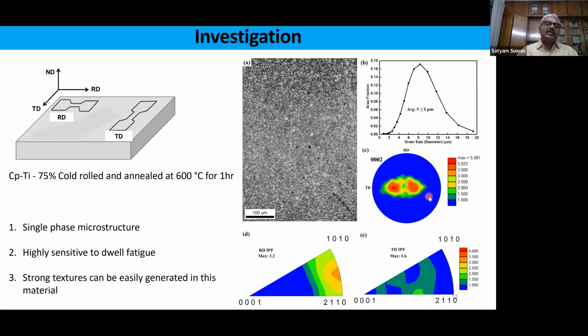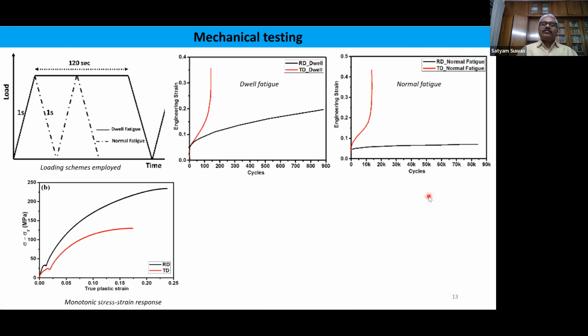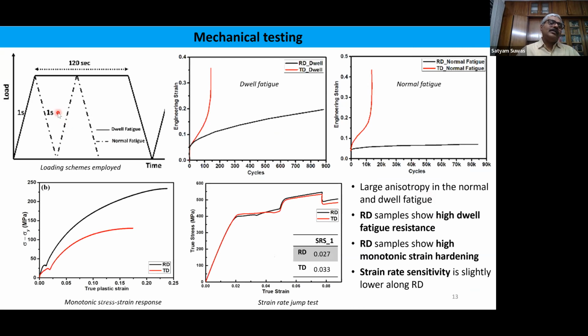And since in CP titanium it's easy to generate a very strong basal texture, we generated it, and then we did the test of this material, and here is the result. So this is the loading cycle that was employed, right? In order to have a comparative idea, we just did normal fatigue with this kind of profile. So one loading and then unloading, loading and unloading. While in the other case, for dwell fatigue condition, after loading we kept it at that load for 120 seconds, 2 minutes, and then unloaded it, right? And then again the second cycle starts in the same way. So this is the normal fatigue, and this we will refer to as dwell fatigue, right?